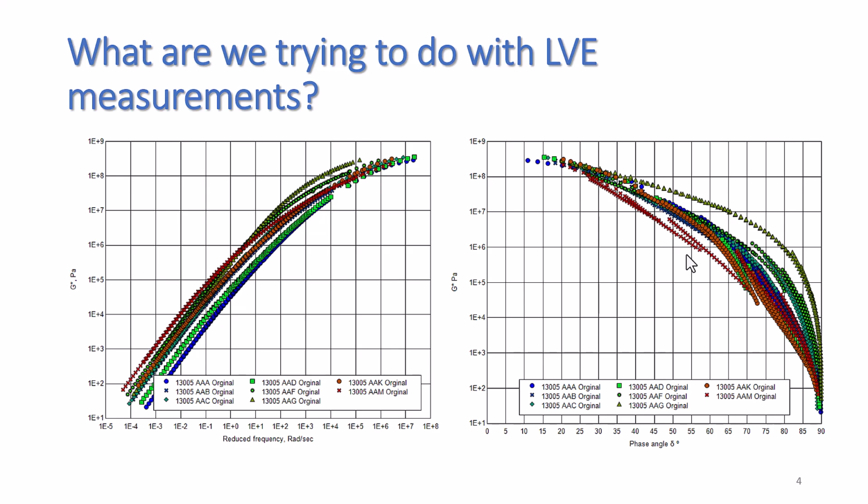The flatter ones might have more asphaltenes typically. So the flatter ones I would describe here as, for example, this binder here, which is AAG, is a California Valley binder, and is maybe more typical of what in the old way of things we would call a sol binder, a low asphaltene content product.